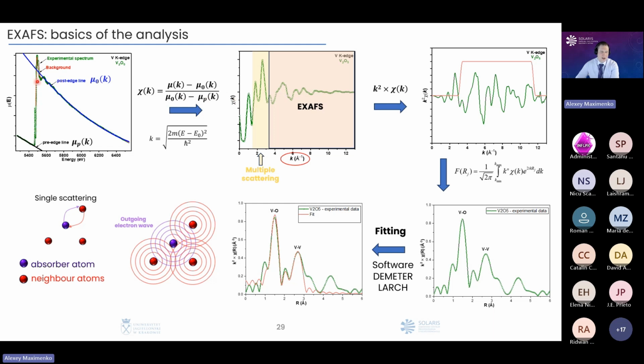As we could see here, this absorption step for us now is a background. We get rid of it. It looks like this. Also, we plot this dependence of the absorption coefficient without the background, not in the energy scale, but in the wave number scale, where this k wave number could be calculated like this, where E0 is actually the position of our absorption edge. Then, in order to see more precisely what kind of oscillations we have here, we multiply this function by k squared, or even k cubed. And that's how we get the oscillation functions.